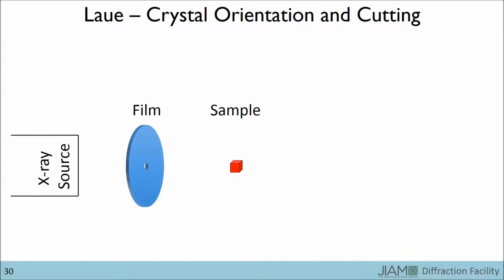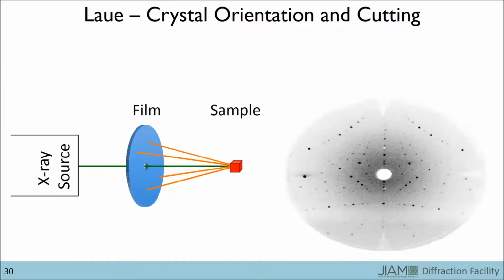In a Laue experiment, we have an X-ray source, some sort of film, and the sample. Just to clarify, the sample does not need to be any particular shape. I just used a cube as an example. The X-rays are shot through the center of the film, strike the sample, and are reflected back to the film, producing a pattern like this. Each one of these dots corresponds to a diffraction peak for a particular atomic plane.